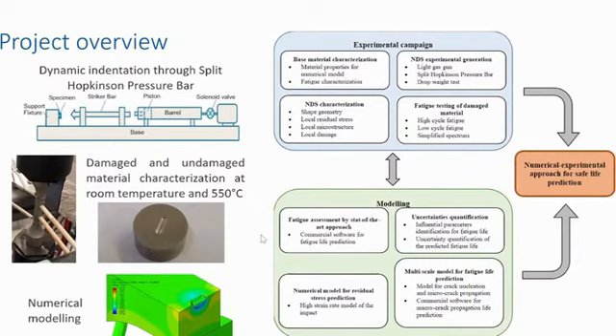Then we use all the experimental data that we produce to calibrate and validate numerical models for the prediction of the residual stress during the impact, and also for the prediction of the fatigue life, taking into account the damage and the residual stresses. And once we have the validated model, the final step is to perform an uncertainty quantification to understand the effect of the different features of the damage on the fatigue life.